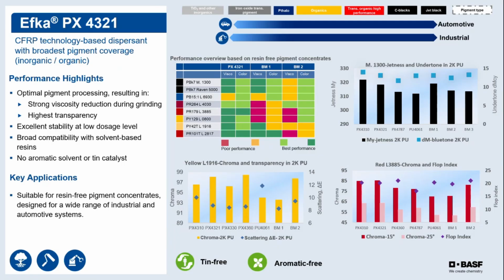And it's a stoplight chart. So darker green means really good, and red means poor performance. And you can see with 4321, when it comes to viscosity, stability, as well as coloristic performance, in general has the best characteristics overall, ranging from best performance to very good performance, and maybe one case where we have a challenge with the pigment blue 15. But compared to the benchmarks, it's doing excellent.